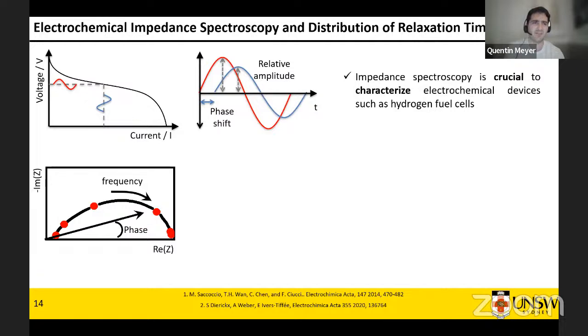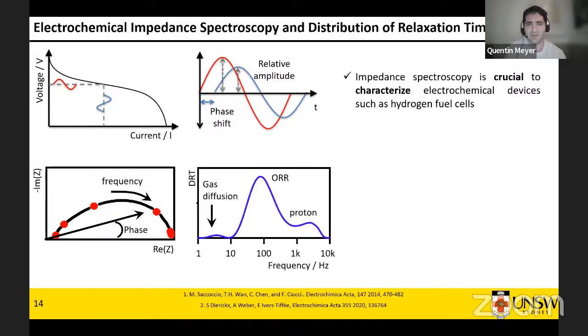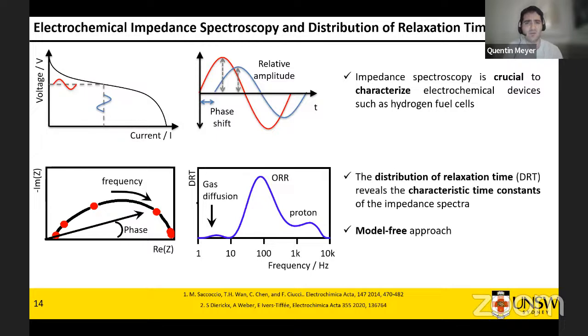So what I've done is some impedance spectroscopy. Basically, you oscillate the current and you record the voltage response, and you do this across different amplitudes and different frequencies, and what you get is called a Nyquist plot over here. Nyquist plots are used a lot by chemists, but the problem is they're quite hard to understand what's happening in. So what I'm going to be using is called the distribution of relaxation time, which is a new tool to analyze impedance measurements. It allows you to basically extract different peaks based on different processes.